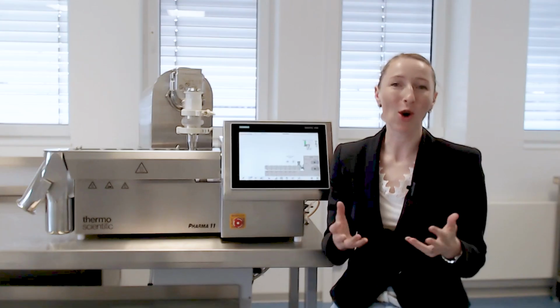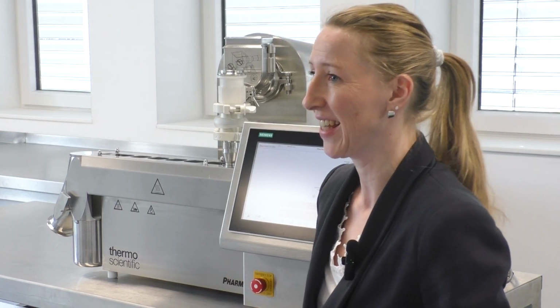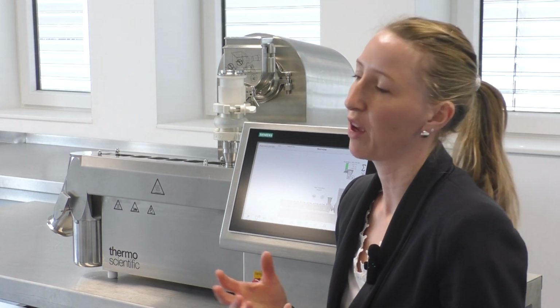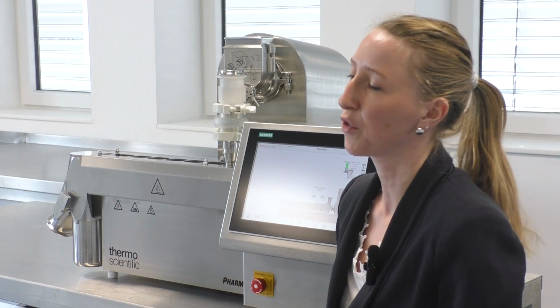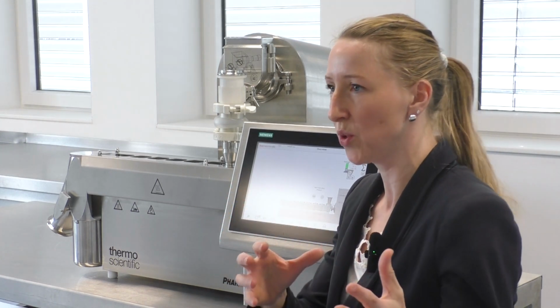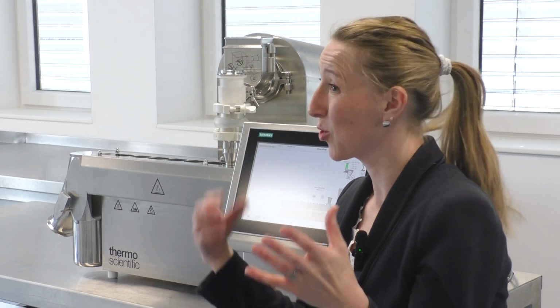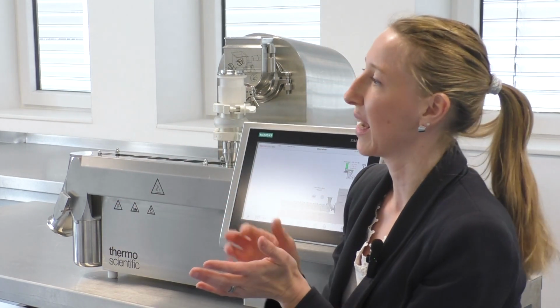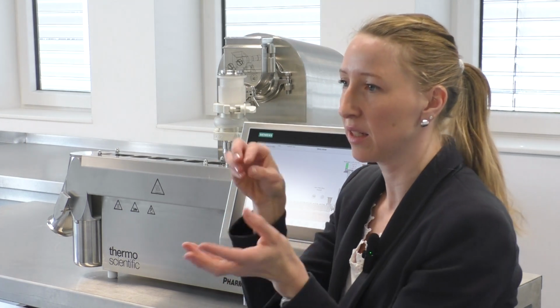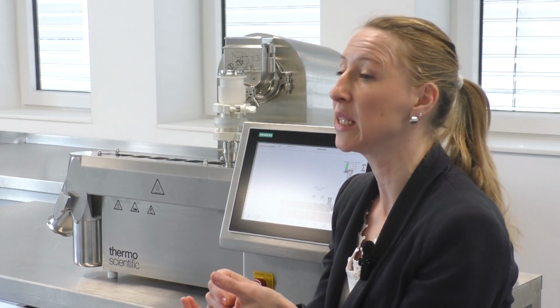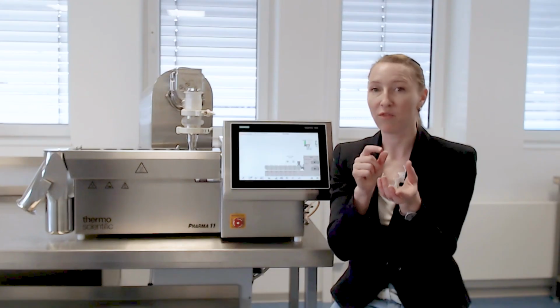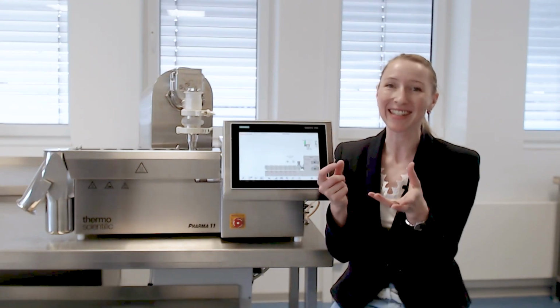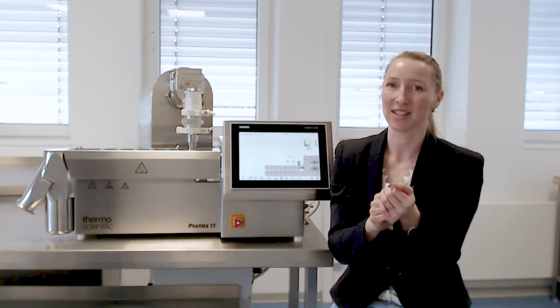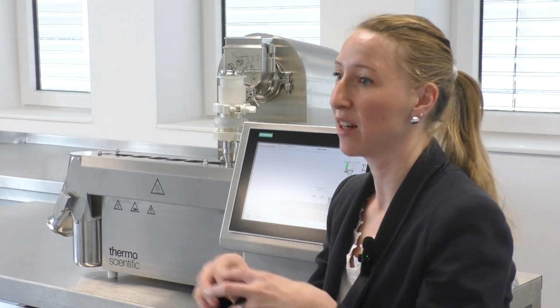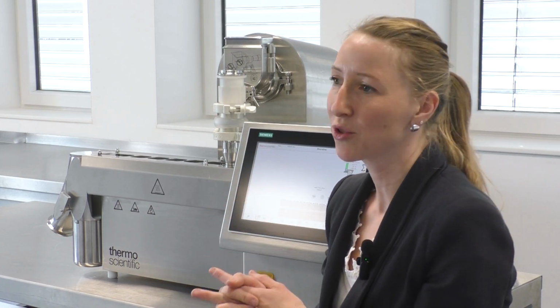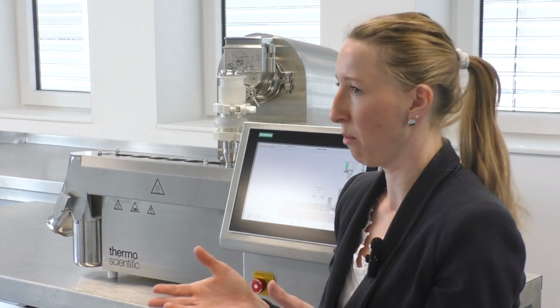And at that point, we talked to the company Grace, who make mesoporous silica, and they had the idea, and they found some research on that in different universities, where you can use that silica and mill it together with the API. And if you do that, you will get a very nice amorphous state, and the API, the active pharmaceutical ingredient, is staying in this very tiny, well, probably not more crystalline state inside the pores of the mesoporous silica. And the silica is kind of stabilizing that state. So a very interesting new research, but they use ball milling for that.